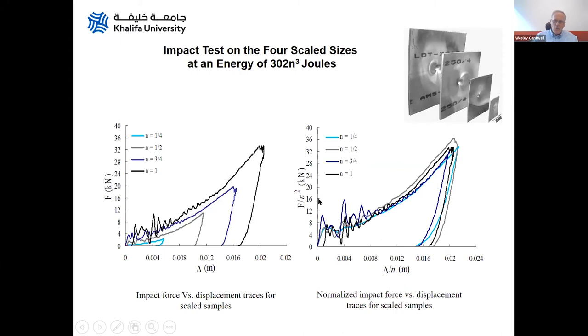Now, as I mentioned before, we normalize our force by N squared, our scale size squared, and our displacement by N. And when we do that, we find that all of our traces collapse neatly one on top of the other. And we get a very nice response there, where our N equals quarter sample is giving a response that is very similar to our much larger plate. There's some dynamic effects occurring here at the beginning due to the very high forces that the load cell is experiencing. But very encouraging there. You can see the plates there in the top right-hand corner, and you can see they've been indented. If you look at the plates, you can see at least qualitatively that the level of damage is similar in them all.